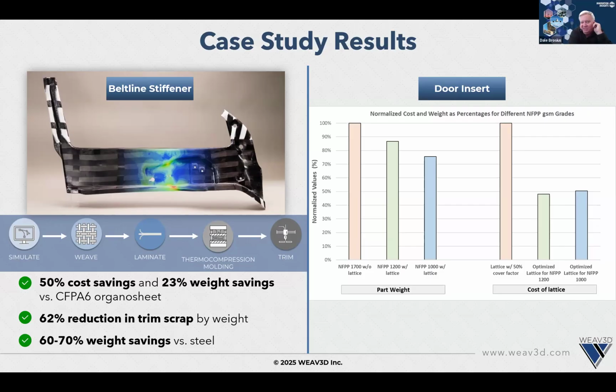So when you mold this, do you have to preheat the lattice like you would in an organo sheet? It depends on the process. If you're doing injection overmolding, that is the recommended route that we would advise: you preheat the lattice, you place it into the tool, and then the injection molding final forms it and gets it to the right geometry.